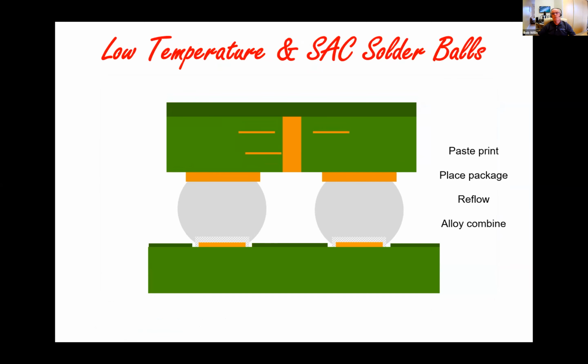So during reflow soldering with either the tin indium or tin bismuth type paste, the material reflows and wets the solder on the SAC ball, just like when we reflow tin lead with SAC balls. The ball does not become a liquid, but the material joins together to form the joint. And the amount of time, the temperature, and the number of reflow operations will have an impact on the combined area, where the tin bismuth and the SAC, in the case of BGA terminations, actually reaches. That's something that needs to be borne in mind when you get more into the impact on reliability of